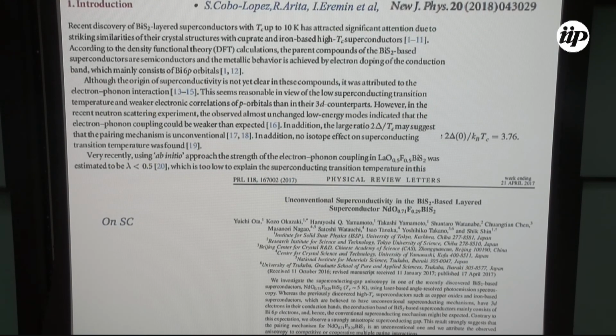And I put this because it's a recent paper by Cobo Lopez, Arita, Eremin, and some other colleagues this year, which is interesting because they review how is the situation with all the other mechanisms which were at some point analyzed as possible sources of superconductivity. And as you see, the latest things are that no isotope effect is found. Also, with the latest ab initio approaches, they don't see, for example, in this compound, strong enough electron-phonon coupling to describe the superconductivity found here.